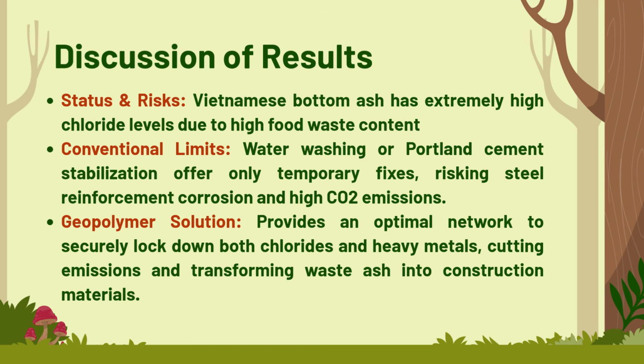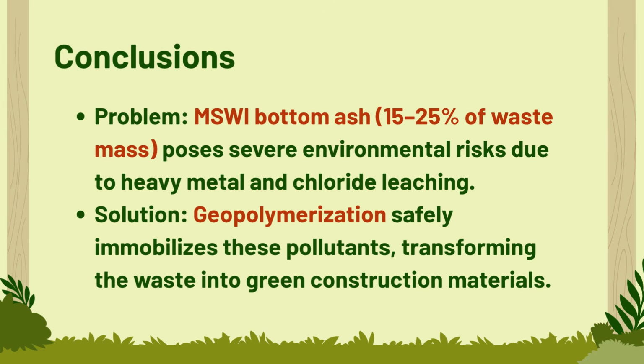The geopolymer matrix can effectively immobilize chloride ions and heavy metals while reducing carbon dioxide emissions and converting bottom ash into valuable construction materials. In conclusion, bottom ash from municipal solid waste incineration, which accounts for about 20% of the input waste, presents significant environmental challenges because of chloride ions and heavy metals. Our results indicate that geopolymerization is a promising solution to safely immobilize these pollutants and transform bottom ash into sustainable green construction materials.